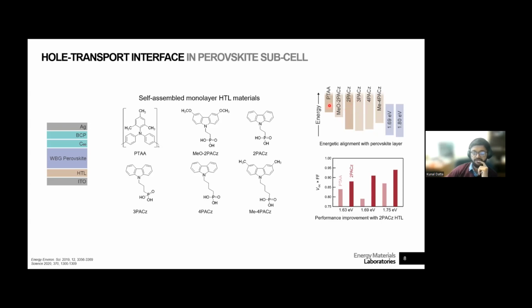And if you compare 2PACz with PTAA, you can see here we take the product of the VOC and the fill factor, which basically translates to an efficiency in the rate of charge collection at that interface, and also the energetic alignment, right? Which basically bumps up your voltage. And you can see that across different band gaps.